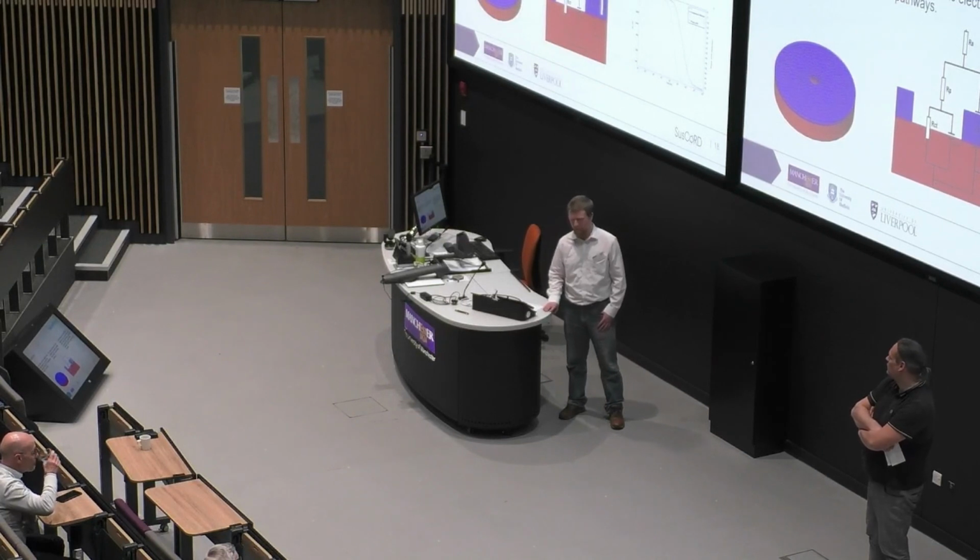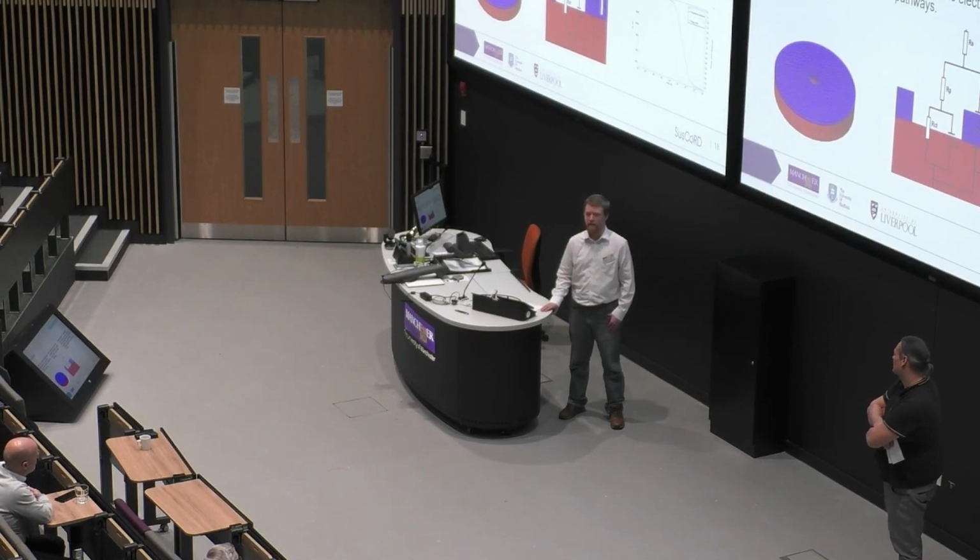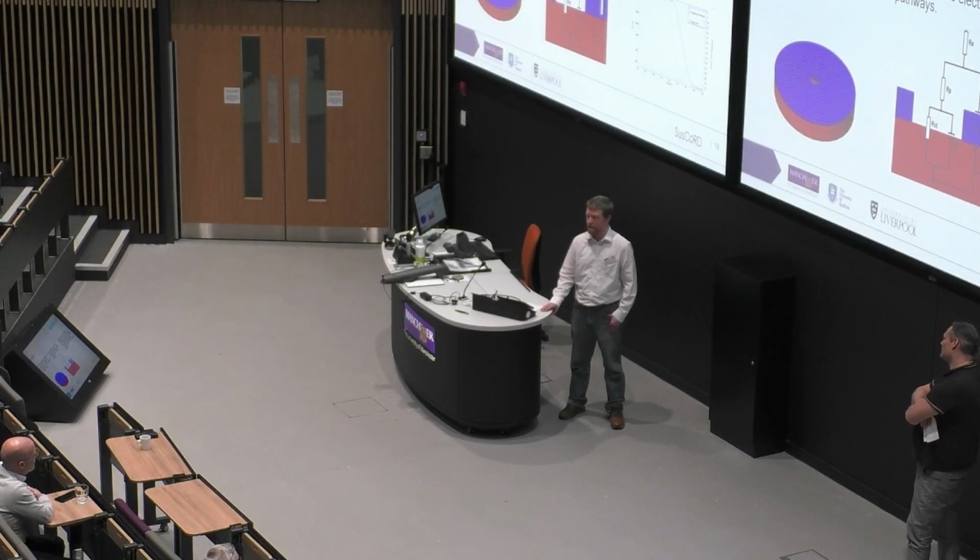Getting into the micron scale will be quite difficult. We can move down to about 1 millimeter quite comfortably using mechanical methods, but anything smaller than that will either require a less controlled method or something a bit more specialized. One of the options we've looked into is potentially lasers, but we'll get to that soon. But yes, going below 1 millimeter is quite difficult. And even if we were able to make, say, a 1 nanometer defect, there would be no hope of measuring anything from that.